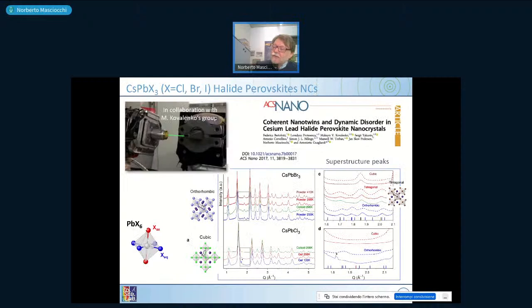Now we go to the last two cases of example. This is one case where we have one of the very famous luminescent perovskites. You see there a capillary filled by a suspension, so it's a solution containing a crystal of cesium lead bromide, which is illuminated by the normal neon light in the lab, and already by normal weak neon light it shines out, emits a very bright green color. The nozzle you see in the back is the synchrotron beam, of course, in this position. Now we were taking a photo with the synchrotron beam shut, but this is a condition where we normally measure our system in capillary, in solution, suspension, so not only as dry powder.